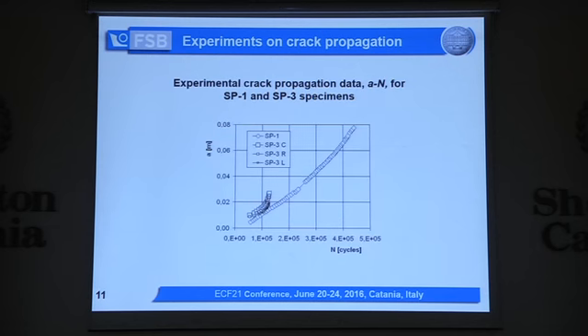And for the specimen with one crack, the welded specimen, this is the fatigue life, and for the three cracks it's much shorter, several times shorter. And what we can see here is not what I showed you before. It was like that, and now it's propagating probably at the same crack growth rate. And this is what we wanted to investigate and to see what was the reason for this.